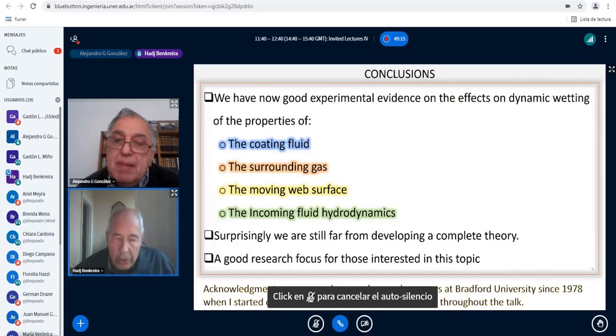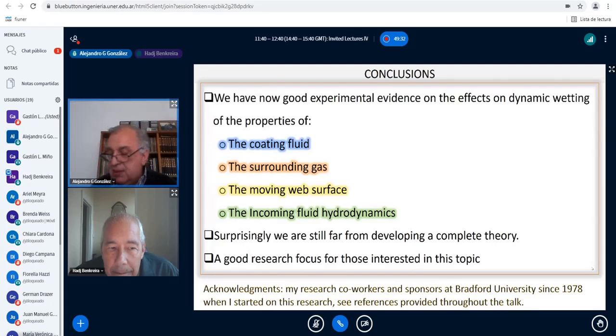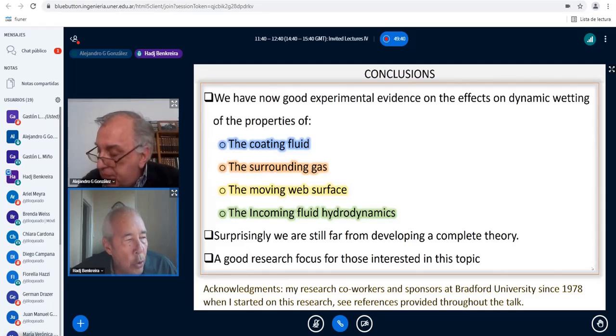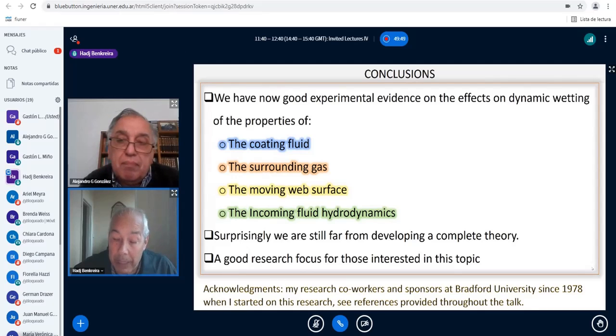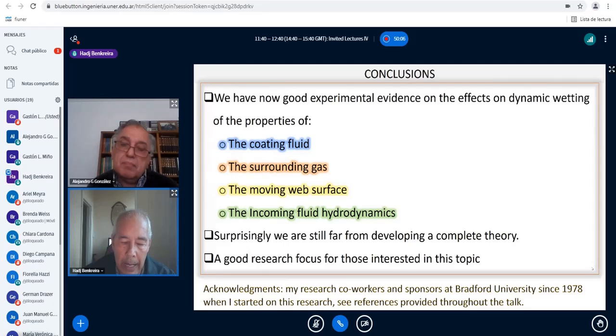Yes. Strictly speaking, if you go to zero pressure, you'll have no gas. So yes, the air entrainment speed would be infinity, or the gas entrainment speed would be infinity. So this analysis is restricted to a particular regime, I say. Yes, it is. In our case, of course, because of our experimental difficulties, we did not go below 10, 15, 25 millibar. All right. But even in that situation, the thin film viscosity is changing. And the way you measure the thin film viscosity, you have to use, because viscosity does not mean anything if you do not look at what you mean by it. And in our experiment, we're talking about viscosity in a gap which is very, very small.